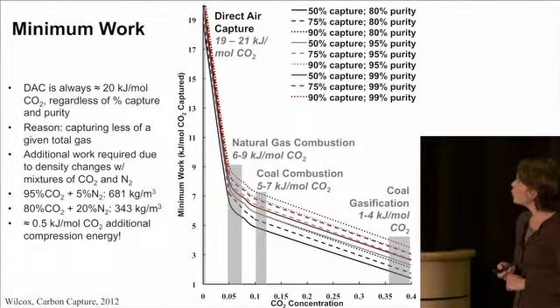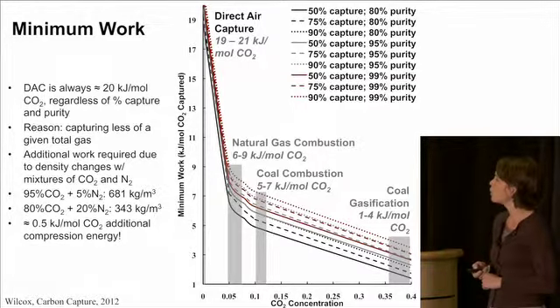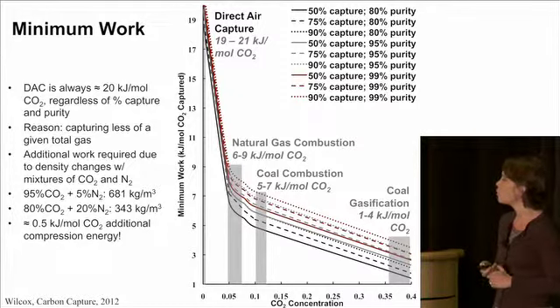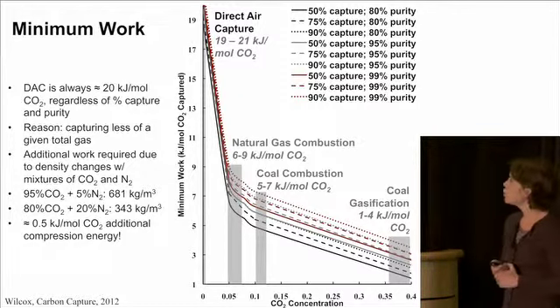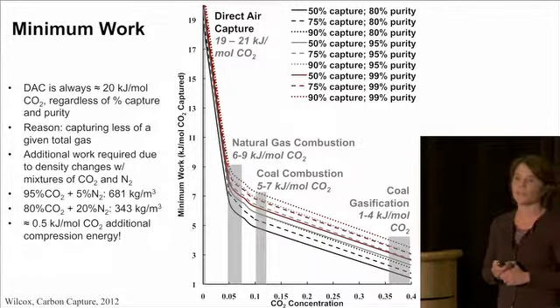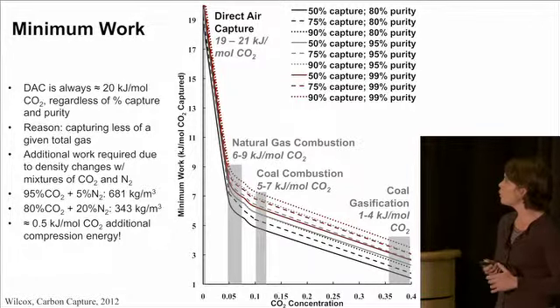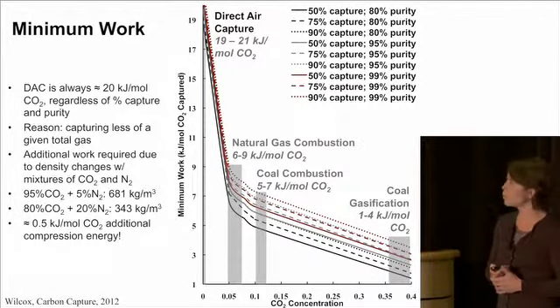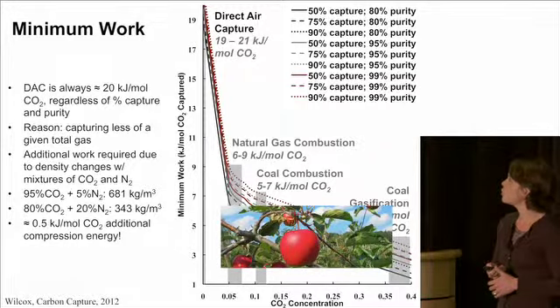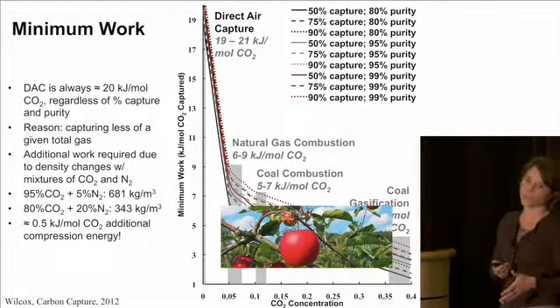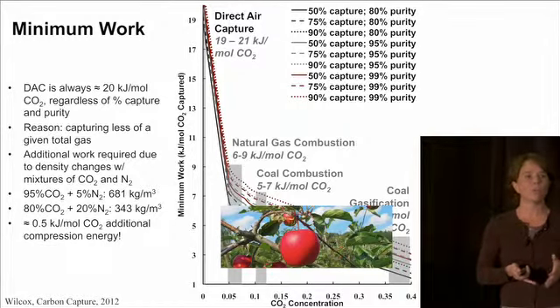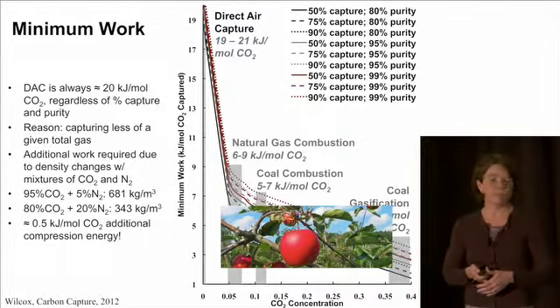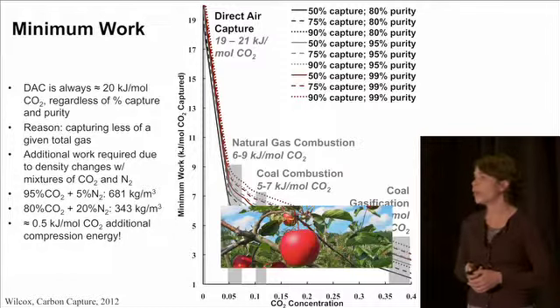If you look at these different scenarios, you can see that the minimum work really is correlated to the concentration of CO2 in a given gas mixture. So you have high concentrations, for instance, in the case of gasifying coal, then lower CO2 concentrations in traditional coal combustion, then natural gas combustion, all the way up to direct air capture. So this motivated our study in terms of looking at the low-hanging fruit, which is essentially associated with more concentrated sources first. So we're specifically focusing on developing sorbents for point source capture, looking specifically at coal combustion and natural gas fired power utilities.